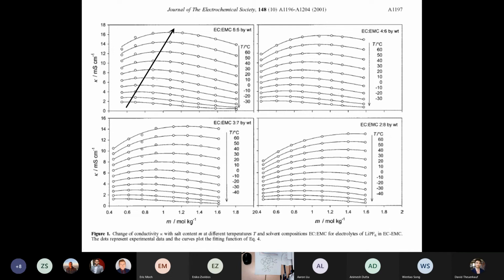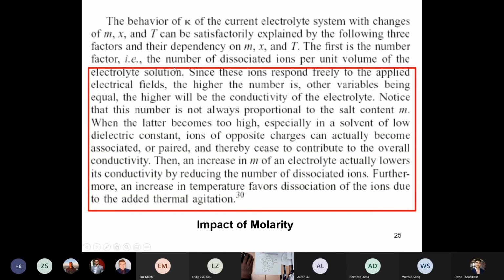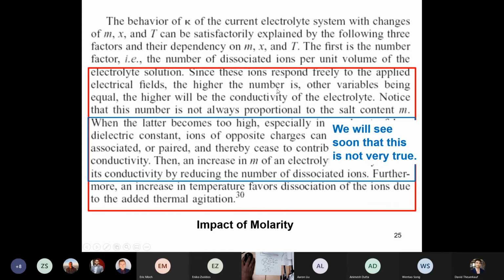And then in their paper, they talk about the reasons for these changes in these curves. So let's see what they have to say. Okay, so they say the behavior of the conductivity of the current electrolyte system with changes in molality, EC to EMC ratio, and temperature can be satisfactorily explained by the following three factors and their dependency on molality, fraction of EMC, and temperature. The first is the number factor, the number of dissociated ions per unit volume of the electrolyte solution, right? Since these ions respond freely to the applied electric fields, the higher the number is, other variables being equal, the higher will be the conductivity of the electrolyte.